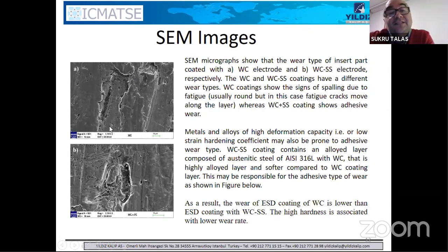This is the fatigue wear, and this seems to be the adhesive wear. So the alloying, in fact, is very good, no problem with alloying, but it changes defect formation, a type of defects in both coated steels. Not sure which one is the best, but what we can do, if the surface is worn, we can clear the surface and do the ESD again.